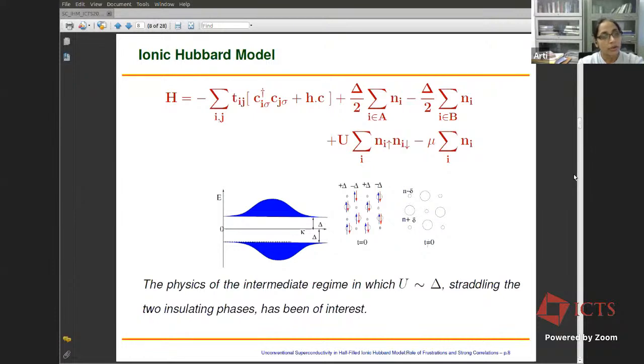And if the U is much larger than the staggered potential delta, then we basically go back to the physics of the standard Hubbard model, and what we see is a Mott insulator. What we see is a Mott insulator basically with the antiferromagnetic order, and no doublons and holons are allowed in this limit. So the physics of the large U limit of the ionic Hubbard model and the large delta limit of the ionic Hubbard model are very simple and straightforward.